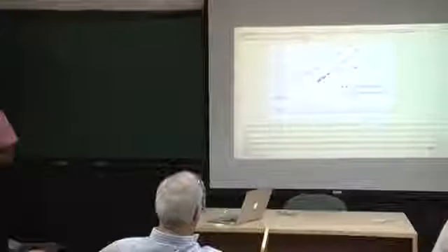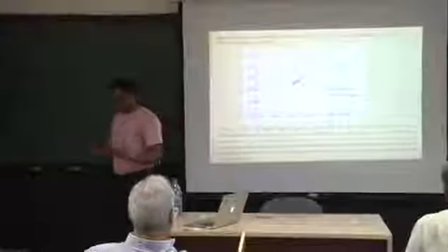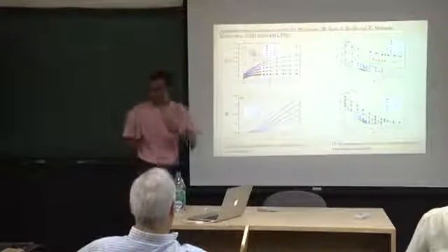So here the mean field picture still holds, and our analysis seems to suggest that this blue line should be something like this, horizontal. Okay. And that is unless our calculation is completely wrong, or there is some issue with this entropy calculation. One thing is clear: anharmonic effects have to be taken seriously, because when your entropy becomes very small, if you do not take anharmonic effects carefully, then you are playing with small numbers, and you see that your entropy actually becomes negative in places.